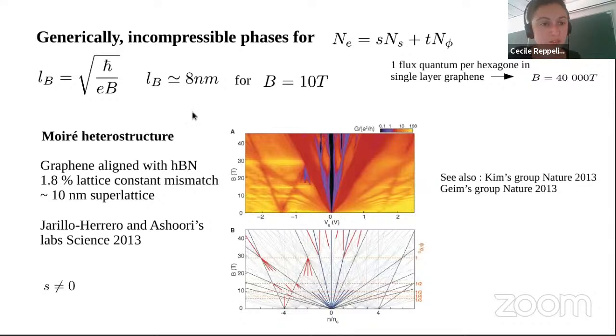So the data here comes from graphene aligned with a substrate of hexagonal boron nitride. Both graphene and hBN are hexagonal, and they have almost the same lattice constant, but not quite. There's a very small 1.8% mismatch between the two lattice constants. When you align those two lattices, this creates the Moiré superlattice with the largest possible unit cell, and it will be around, or maybe a little bit more than, 10 nanometers.